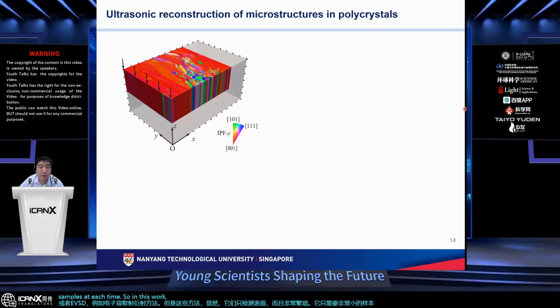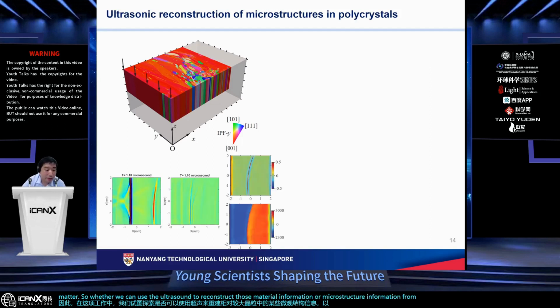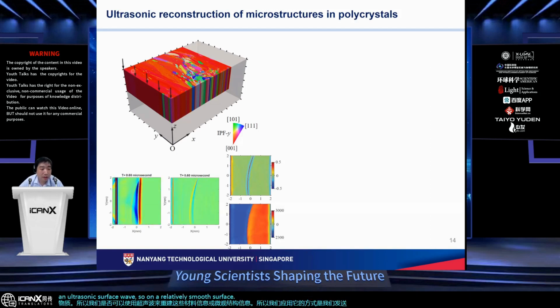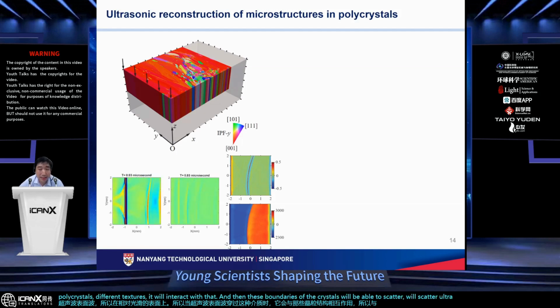So in this work, we are trying to explore whether we can use ultrasound to reconstruct certain microstructure information in the grains, relatively big grains, of course, since the ultrasound wavelength matters. The way we applied it is that we send an ultrasonic surface wave on a relatively smooth surface. When the ultrasonic surface wave is going through this medium, it will interact with those grain structures, with polycrystals and different textures. The boundaries of the crystals will scatter ultrasound. If we are able to capture these scattered signals, then obviously they contain the information of the grain boundaries.